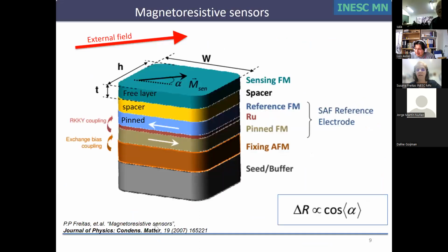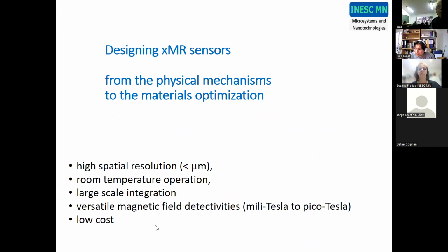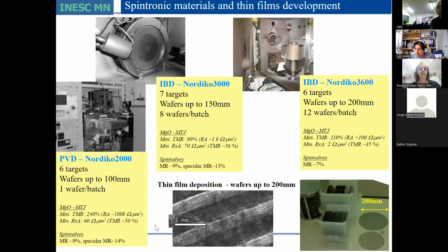We have three sputtering tools that are fully dedicated to thin film for spintronics. Of course, we can also have other targets installed, but we have, for example, this small tool. This was the sputtering tool that has 6 targets. The wafers are 4-inch. Then we have the other machine with ion beam. We have 7 targets and 6-inch wafers. But then it runs batches of wafers, so it's not one single wafer, it's a cassette loaded. And then we have another big machine that also handles 200 millimeters, so 8-inch wafers and 12 wafers per batch. Actually, this is not updated, we upgraded this machine in the last 2 years. So during COVID, we received one extra module for this machine. So we have 8 more targets available in the same tool. So the number of targets is quite important.